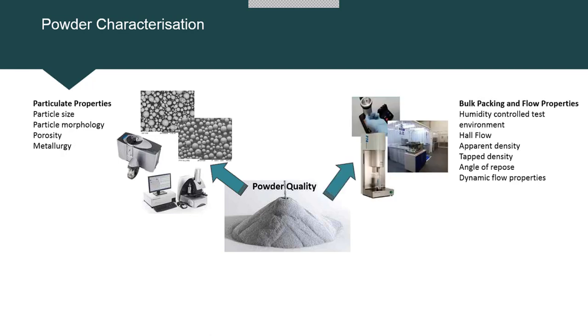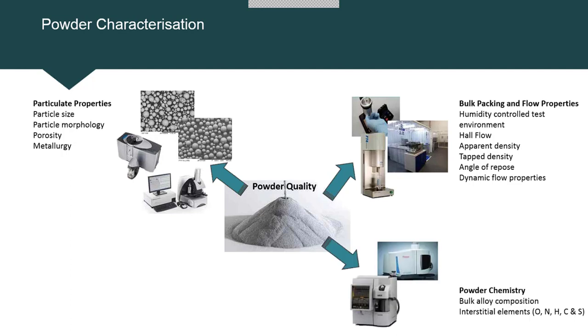You've then got your bulk packing and flow. In this case, we're interested in how those particles in assembly flow in a bulk scenario. So do they flow well? Do they pack well? Then you've got your chemistry. So bulk alloy composition. Titanium 6-4, for instance, do I have the right composition of vanadium and aluminium? But also interstitial elements, so do I have the right composition of oxygen, for instance?